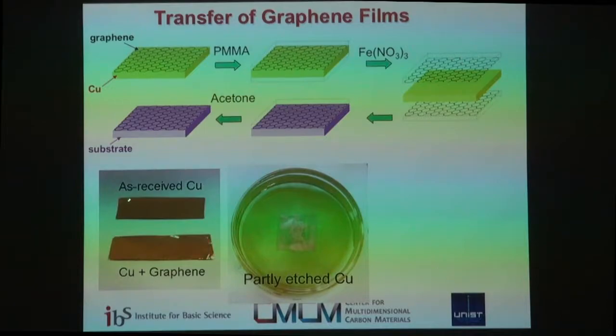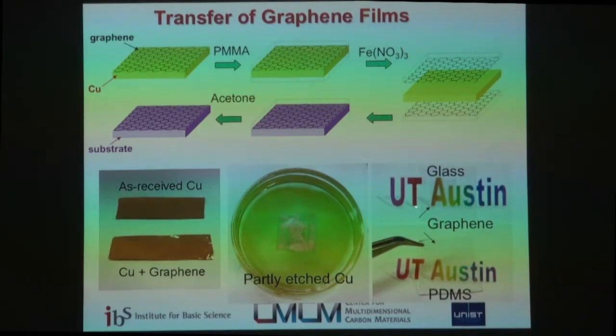But as we received our cold rolled copper foil, it turns out that when you heat treat that, you get mostly 100 orientation, which is not necessarily favorable for making really large, whole foil single crystals. Nonetheless, even with many different grain orientations as per electron backscatter diffraction, we got monolayer graphene over the whole foil. And then it could be transferred to other sorts of substrates. Qingkai Yu, when he was a research professor at University of Houston, with growth of multilayer graphene on nickel, showed that if you supported it with a thin polymer layer, then you could dissolve away the underlying metal.